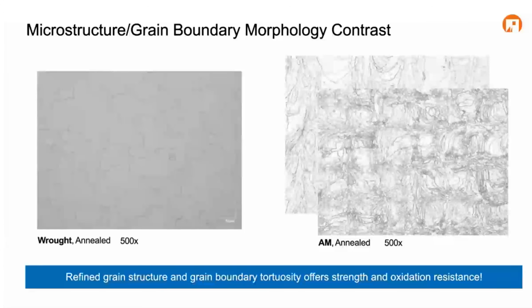Diving deeper into the microstructure and grain morphology, I talked about the cellular type grain structure with pretty planar grain boundaries versus the laser powder bed fusion process, where we see really tortuous grain boundaries forming, with a really refined grain structure. This is going to have benefits when we start talking about oxidation resistance.